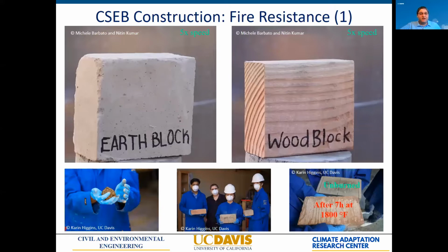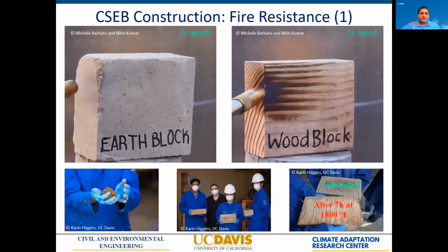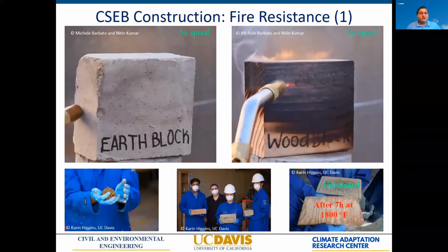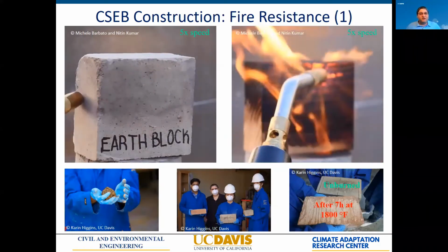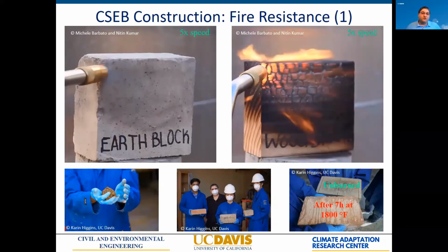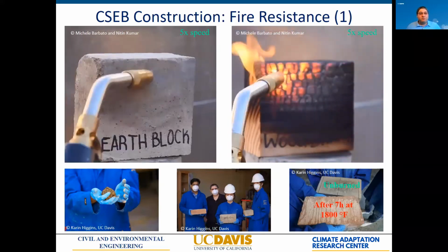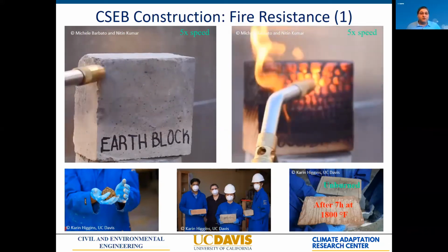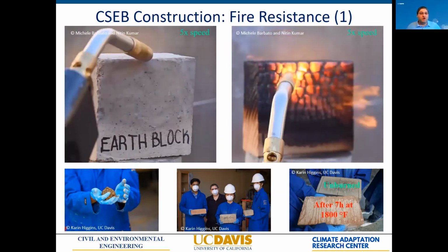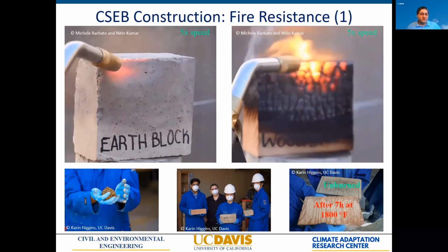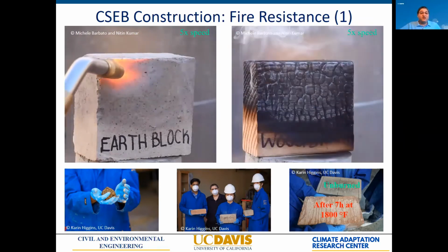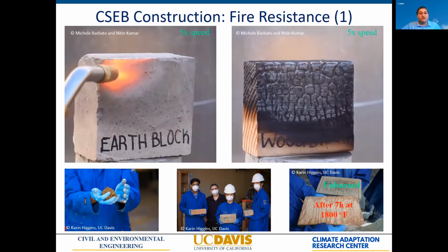So we are investigating the performance of earthen blocks here just as an example of what happens, as you can imagine, when you subject wood and earthen blocks to fire. In this case, this is a propane torch at 3400 Fahrenheit. The wood is immediately charred, while our earth block has a little bit of change of color, but nothing much happening. And we are testing these materials in the furnace, and we found that even after 7 hours at 1800 Fahrenheit, which is much more than the requirements for non-combustible material, our blocks are still practically with no damage.